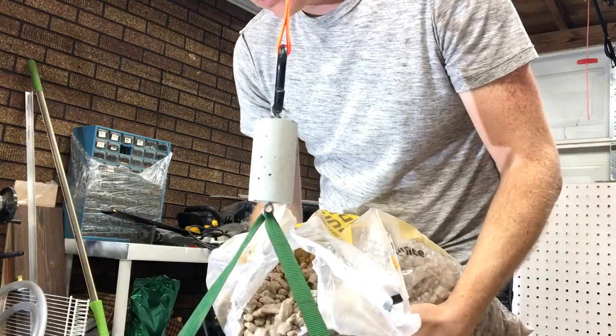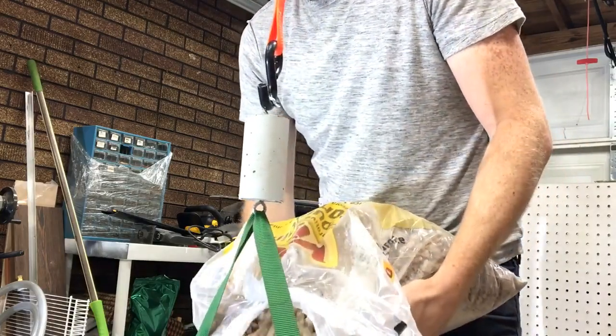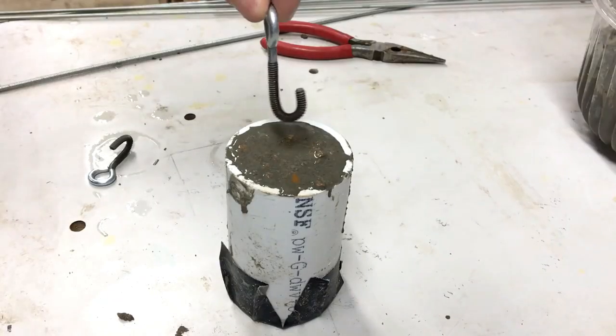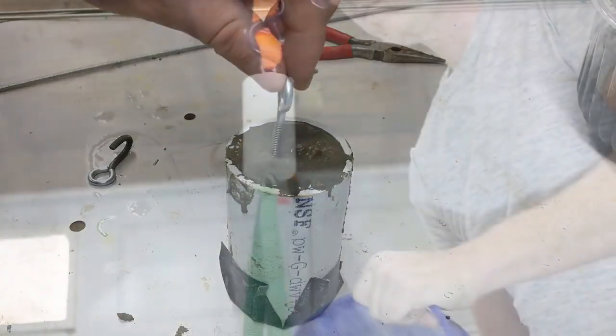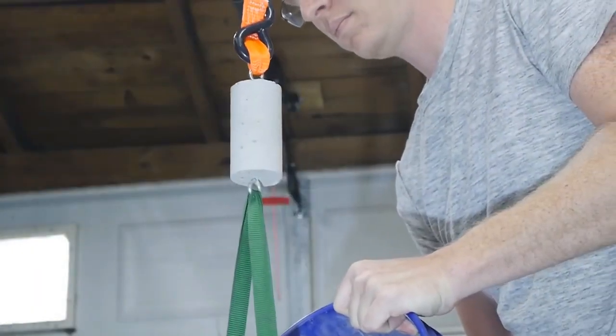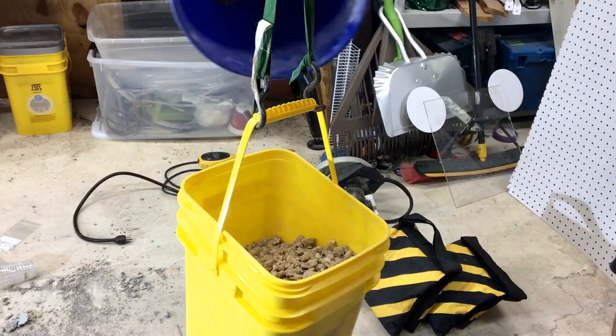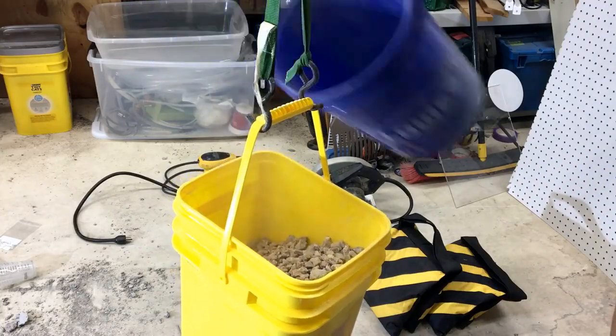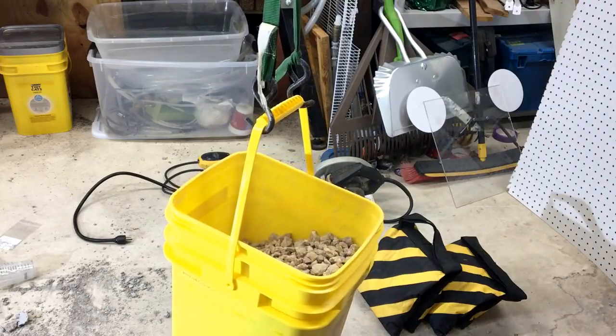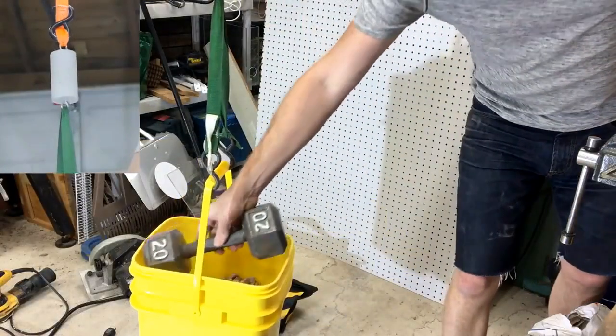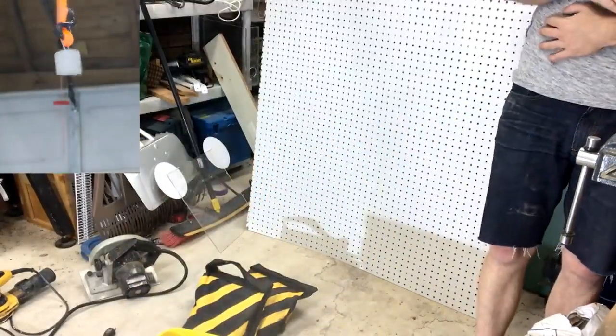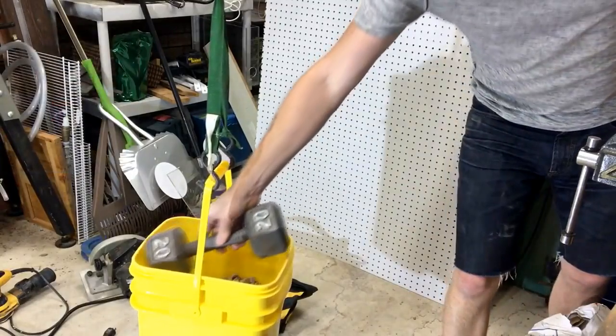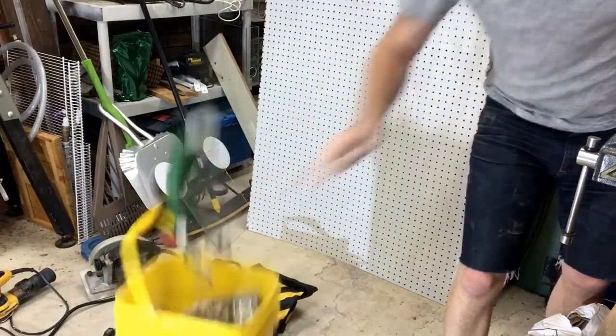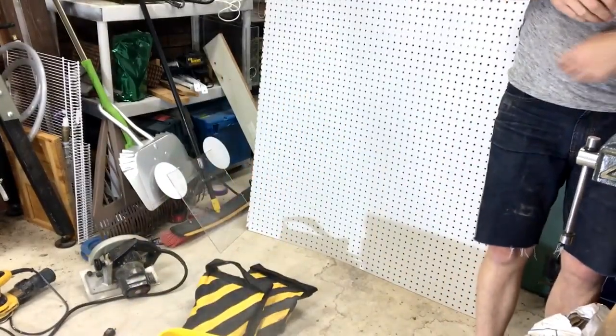The reason is my rig to test tensile strength isn't quite as sophisticated. I cast some eye bolts into the sample, and now I'm hanging it from the rafters in the shop. I filled up this bucket with gravel, but it wasn't quite enough weight to fail the sample, so I added another dumbbell to push it over the edge. The weight of this bucket was only about 80 pounds, or 36 kilos. That's less than 10% of the compressive strength. All this to say, you shouldn't make a rope out of concrete.